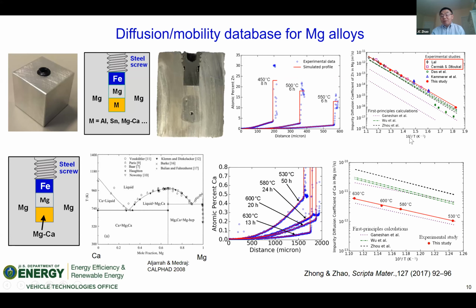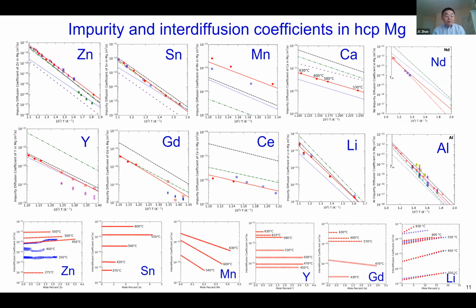And then we can compare with the first principles calculations. You can see that the activation energy is quite good. That's the slope. But the D sub 0, that's how far away this curve is from the measurements. It has more variations. We went ahead under the DOE program to measure 10 different elements in magnesium. Again, we got more measurements than the rest of the world combined, in terms of the tracer, impurity and interdiffusion coefficient data.